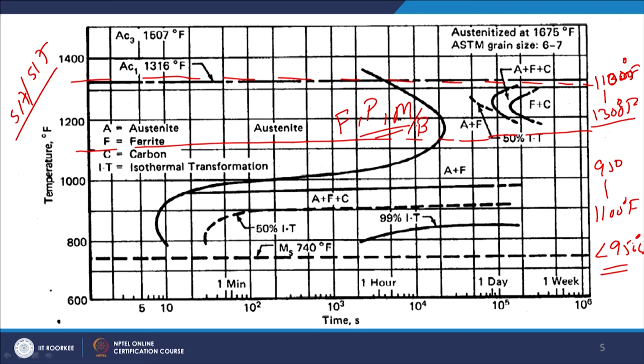So, the formation of the upper bainite, the pearlite and the bainite in these steels leads to a reduction in the yield strength and a reduction in the notch toughness, and in general mechanical properties are adversely affected when the Q&T steel is exposed for transformation at a high temperature for a longer time. This leads to the formation of basically ferrite and upper bainite, and this structure is coarse, which leads to the reduction in the yield strength as well as notch toughness.